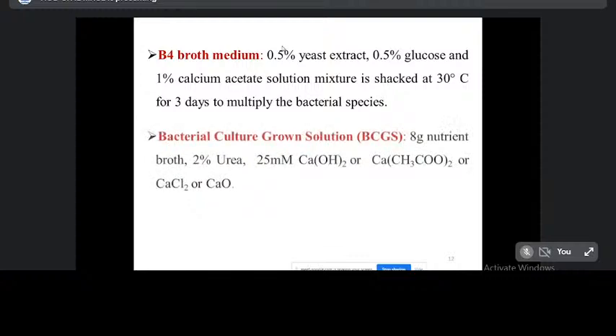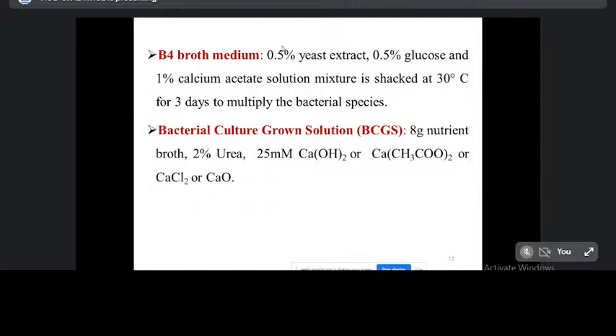In addition to that, these two are B4 broth medium and bacterial culture grown solution. These two solutions are very important. For initial growth of bacteria, I have used B4 broth medium. It is nothing but 0.5% yeast extract, 0.5% glucose and 1% calcium acetate. This solution is shaken at 30 degrees centigrade for 3 days to multiply the bacterial species.